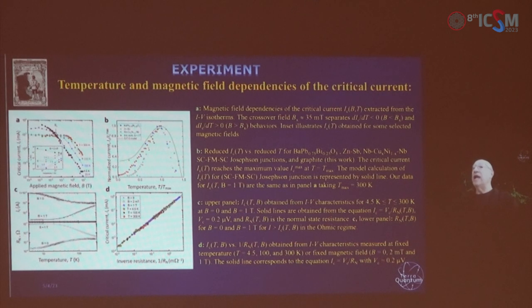And then again in panel C, we show the behavior of the critical current as a function of temperature for these two regions. And what we finally represent in our experimental measurements is the connection between the critical current and the inverse normal resistance, which is exactly the connection we have in the Josephson junction. And what is remarkable is that this resistance is the normal resistance of a bulk graphite sample.